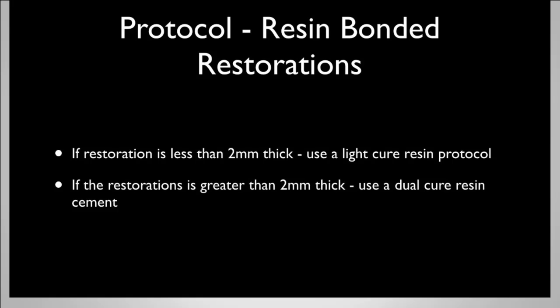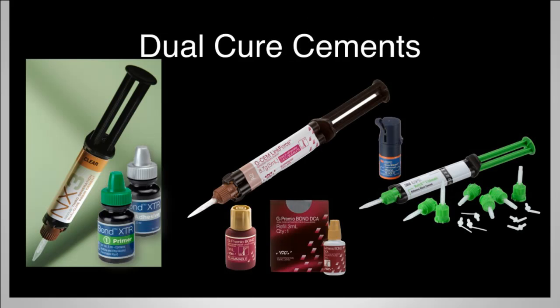When choosing a resin cement, one of the first things to consider is light accessibility. Do we have enough ability to transmit light? When restorations are less than 2 millimeters thick, I generally use a light cure cement. And when they're more than 2 millimeters thick, I use a dual cure resin cement. There are many, many good dual cure resins on the market today, but one of the key factors I look at is compatibility. We need to make sure our dual cure resin cements are compatible with our adhesive of choice.